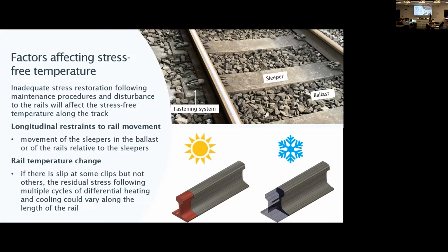So the first factor is the longitudinal restraint to the rail movement. The longitudinal resistance is provided by the fastening system and the ballast. And if either of them, the clamping force of the fastenings or the ballast condition, is poor, the rail can shift, and thus the stress-free temperature will be affected permanently.